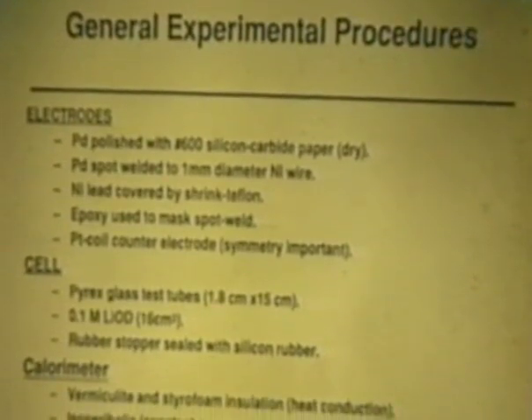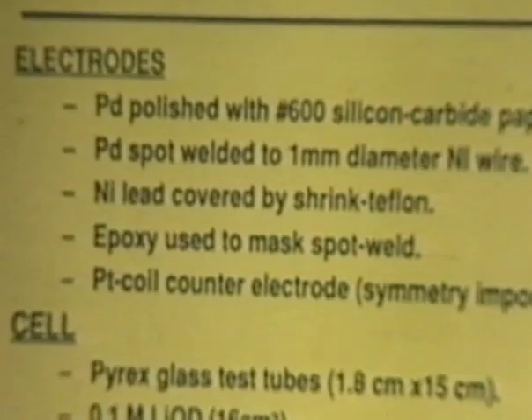we use a Pyrex glass tube, a test tube, 0.1 molar lithium deuteroxide, LiOD, in our calorimetry. And we usually start off with low currents for 7 to 10 days to charge the palladium, and then we switch to higher currents. This is a protocol that we've been told to use. Then we usually run our cells around 40 to 60 degrees Celsius at 400 to 600 milliamps as a typical experiment.